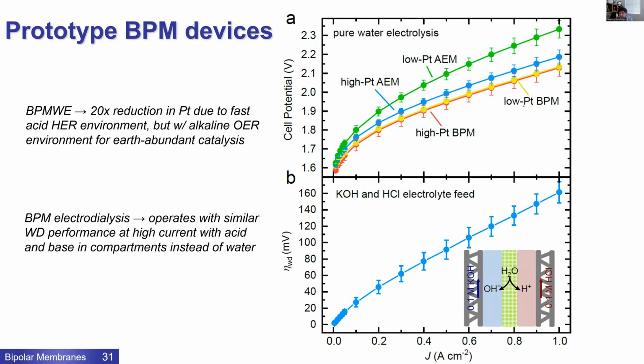I'm going to blow through this pretty quickly, but you can show, for example, that the local microenvironment advantage is there. I don't mean that this is a commercializable demonstration, just a demonstration. If you have a bipolar membrane and you use a high or low amount of platinum at your cathode, it just doesn't matter because platinum is such a good catalyst in acidic conditions. But if you go to an alkaline membrane electrolyzer where the kinetics of hydrogen evolution on platinum are at least 100 times slower, and you lower that same platinum amount, you really have a huge performance hit. So this really shows that the local environments matter.